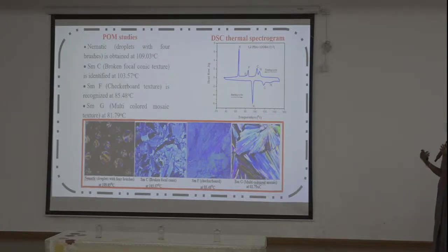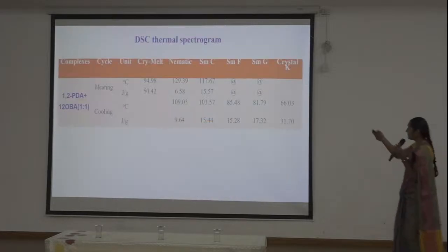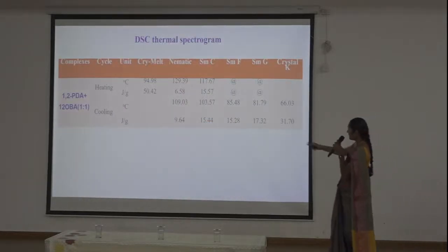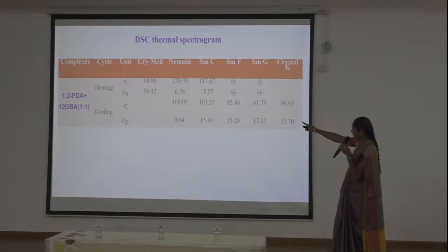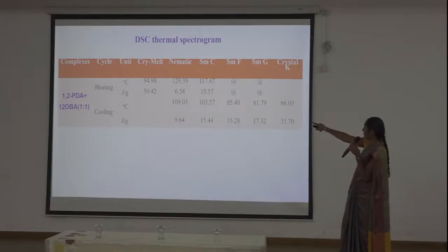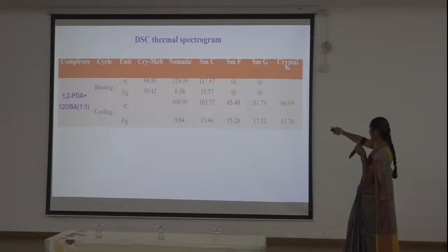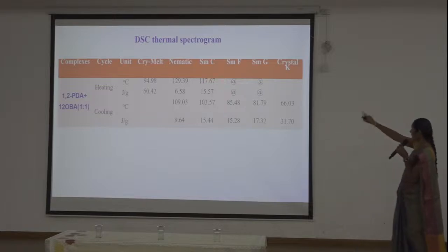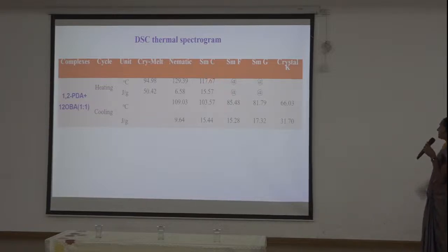After reducing the temperature further, the compound reached the crystal phase. This is the thermal spectrogram reading, showing the cooling pattern. So at 109, 103, 85, and 81 degrees, we observed the nematic, Smectic C, Smectic F, and Smectic G phases, along with the enthalpy values in joules per gram.